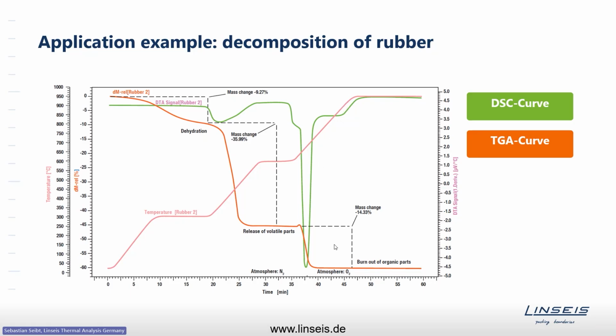And this third heating segment in oxygen shows a very, very rapid mass loss and a very big peak again on the DSC curve. And this is the burn off. So this is the burn off of the organics you formed during pyrolysis in the second decomposition segment here.